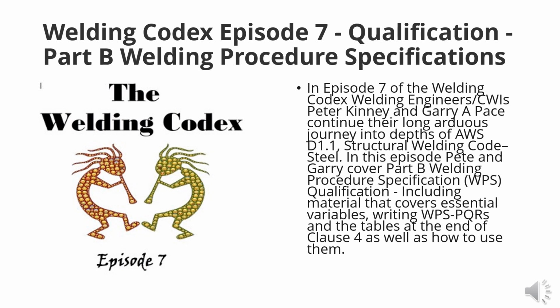2015 on table 4.4. As we've said before multiple times, if you're going to be delving into these codes, you got to be able to find tables, and there's 5 or 6 of these that are used quite a bit. And if you're going to qualify fillet welds, table 4.4 is the one that you're going to use. And it's just 3 macro etches, and it gives you up to unlimited as far as the plate and pipe thickness, and then it tells you the max and the min sizes tested. So I'm pretty sure it's probably 6.4 in 2020, right, Pete? You're correct.